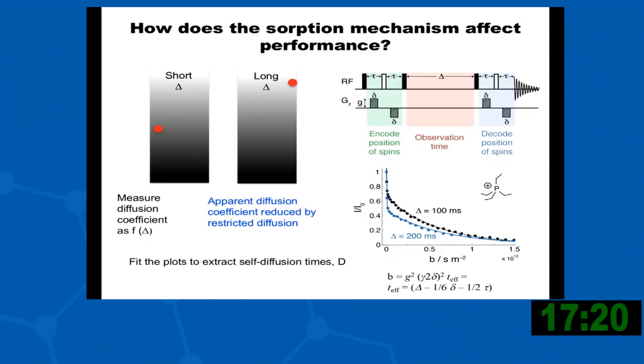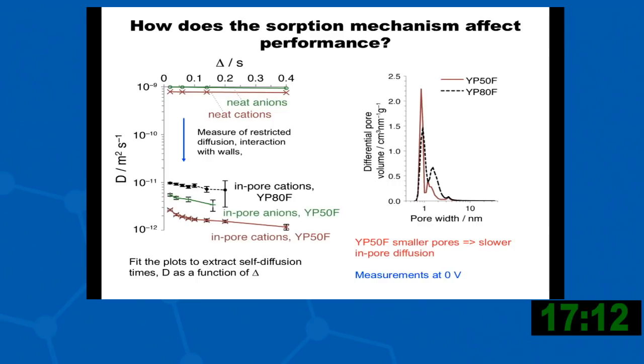And the longer you wait, you can distinguish between ions that are constrained because of pores, and the ions that can move in free environments. And so this is now a plot of the solvent. This is the diffusivity for the solvent versus the confined system. And you can see there's a decrease in the transport by 2 to 3 orders of magnitude between the anions and cations in a neat solvent and inside the pores. So that's not too surprising.